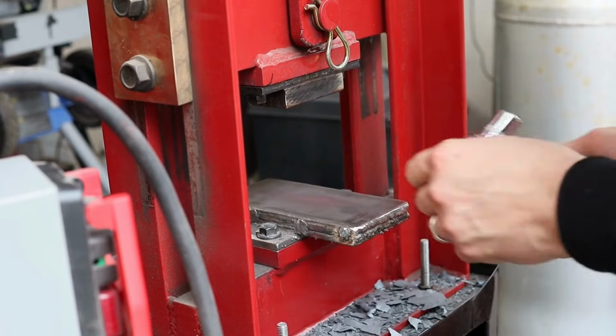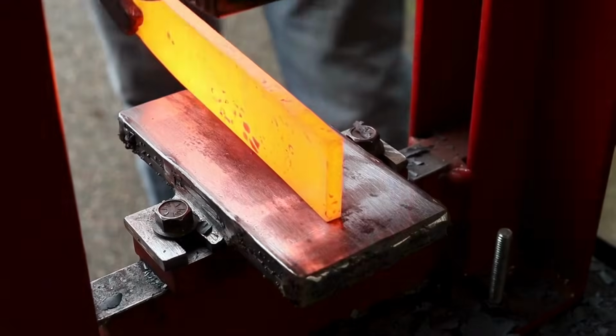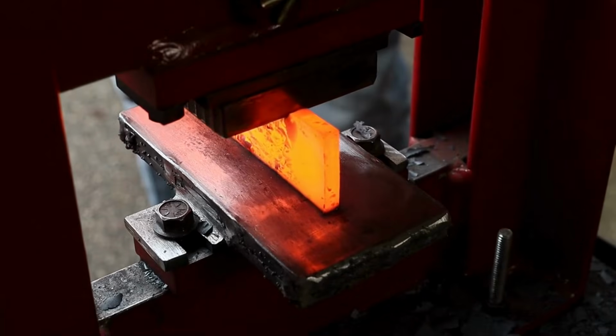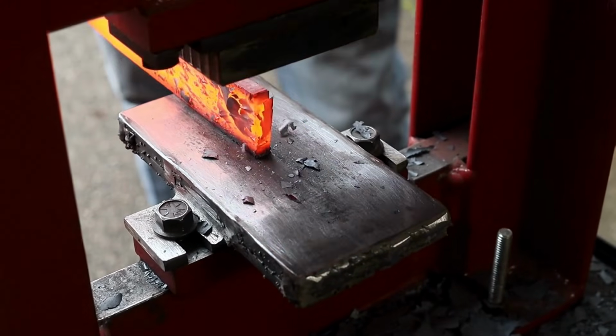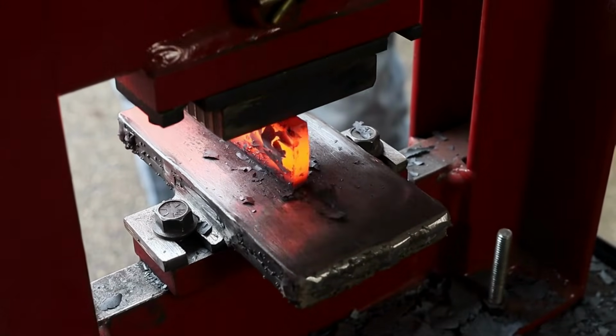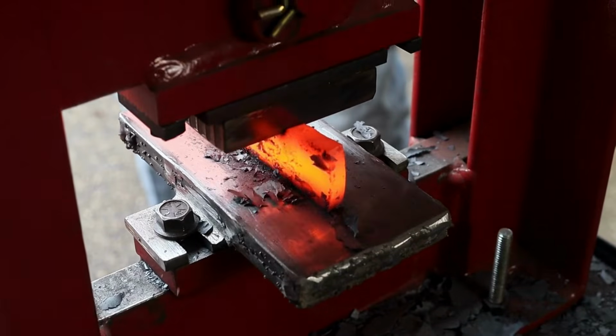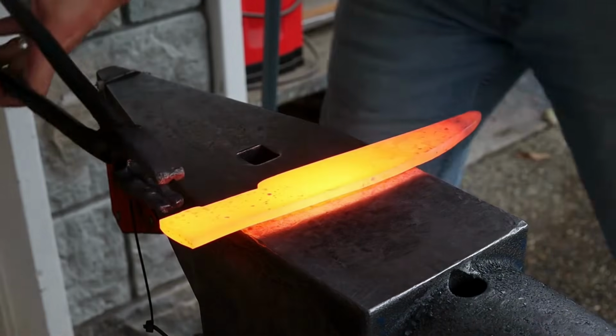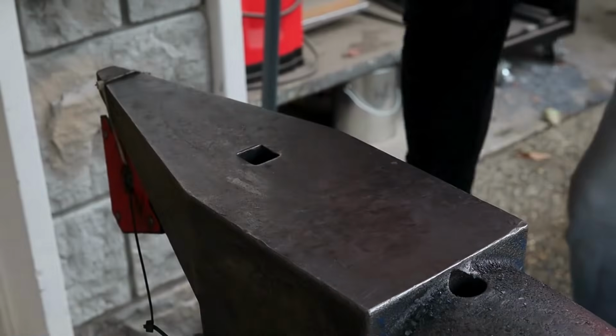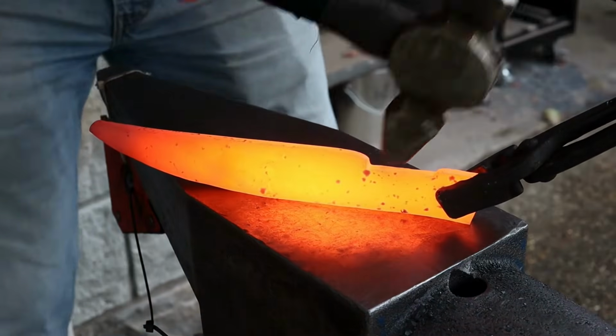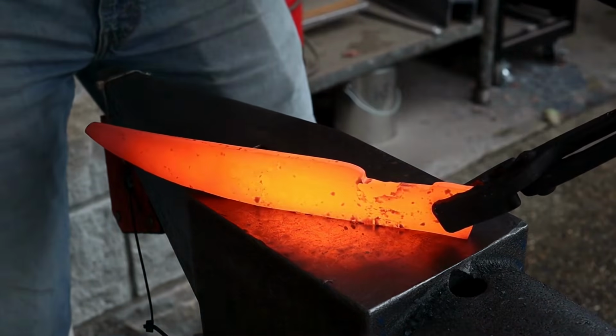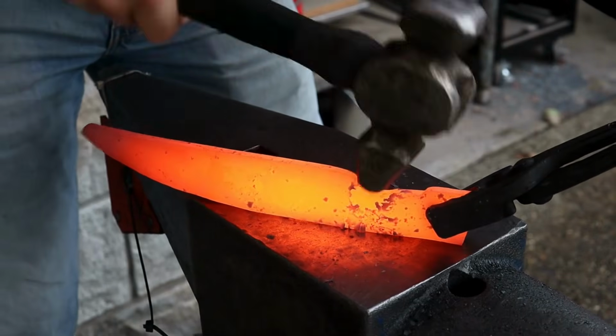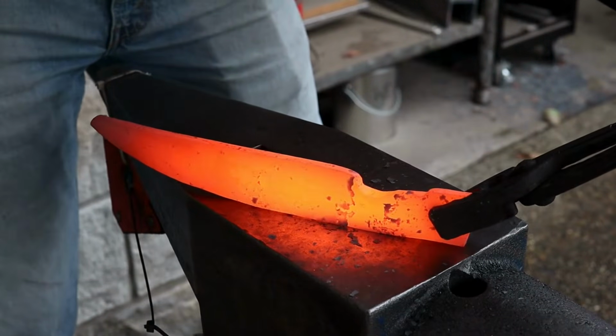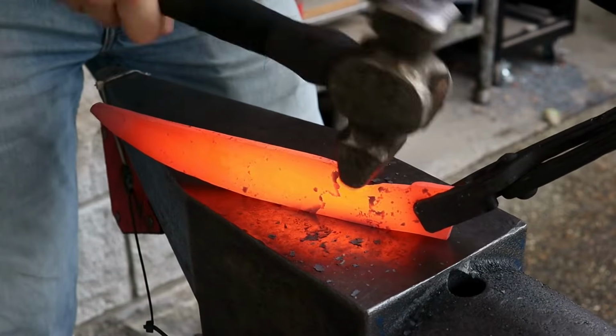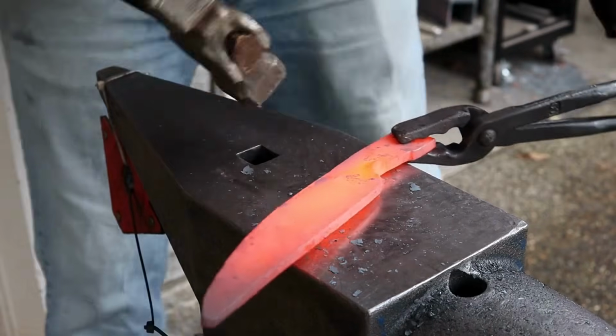Here I'm using a flat die on the top of the press to isolate the material for the handle. I like to use the cross peen of the hammer to shape the front finger choil, or the area where the handle transitions into the blade. You do need to be careful of any cold shuts you could introduce by forging over these creases left from the press. It's a good idea to go over the whole area with a grinder after forging.